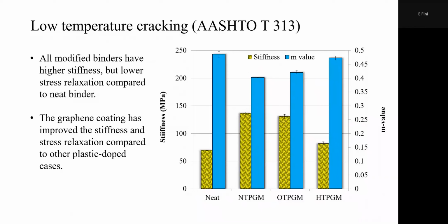Now it's talking about low temperature cracking. So you may have a case that you're improving rutting, fatigue, viscosity, and then it gets to low temperature cracking, you can lose it there. If it's not improving, then you can still not use it, because we have a bunch of specification thresholds for low temperature cracking. As you know, with stiffness and M value, we have to meet those as well.